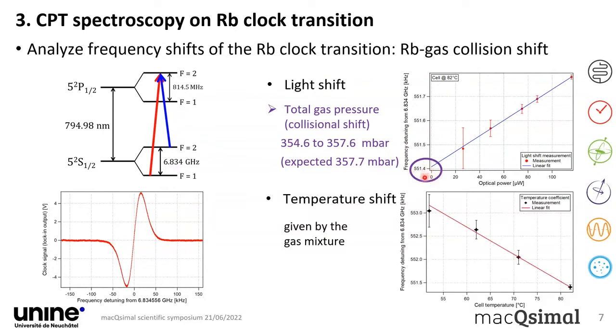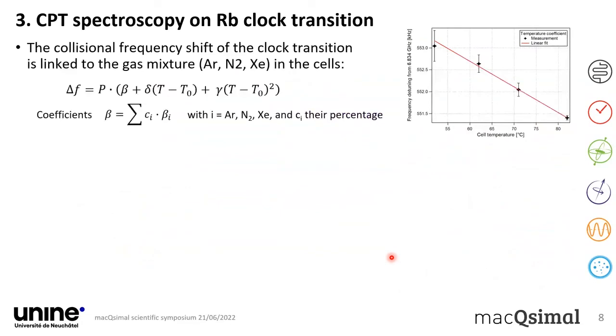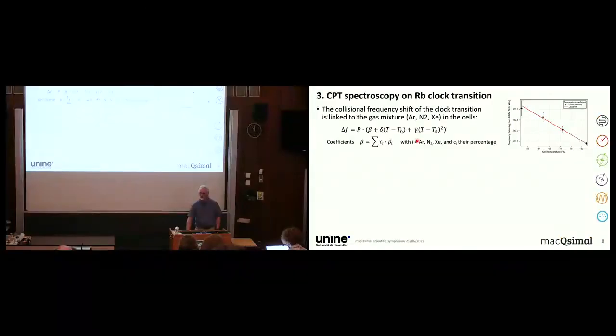Now, in addition, this frequency we can then measure as a function of the temperature of the cell. And this also gives us some dependence, and this dependence allows us then to infer the gas mixture if the temperature shift coefficients are known. And these are known. Here is the well-known theory that you can find in the Vanier-Audoin book on atomic frequency standards. So the frequency shift is just the pressure multiplied by an expansion of a second-degree polynomial around a given temperature of reference. And there are the beta, delta, and gamma coefficients that represent the total shift of our frequency. The delta is a linear coefficient of temperature, as it is shown here in this example. And then you may have a quadratic coefficient, which usually is much smaller.